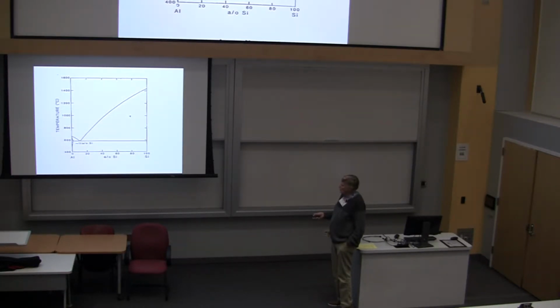You have this eutectic here, and so in fact you could grow silicon crystals out of aluminum by just starting with a melt composition over here somewhere and cooling down. What this phase diagram means is, for example, if you're at 20 atomic percent, as you come down to somewhere around 800 centigrade, you'll start precipitating out silicon. And in order to do a growth of this kind, you need some kind of crucible to hold this in.